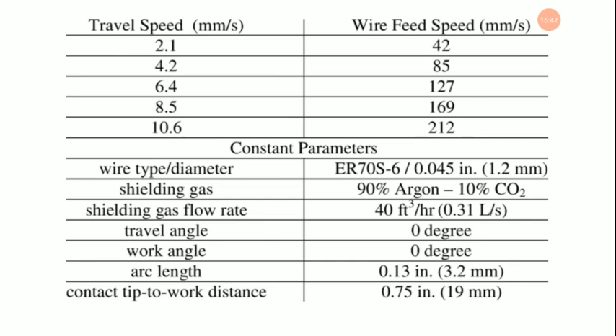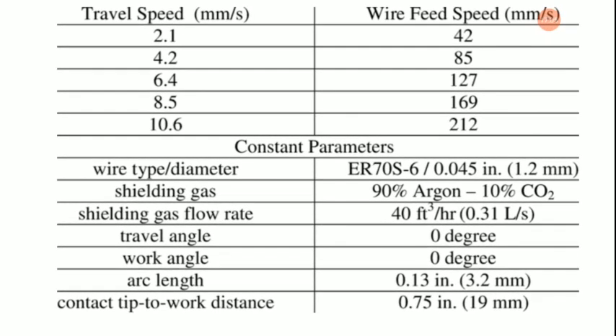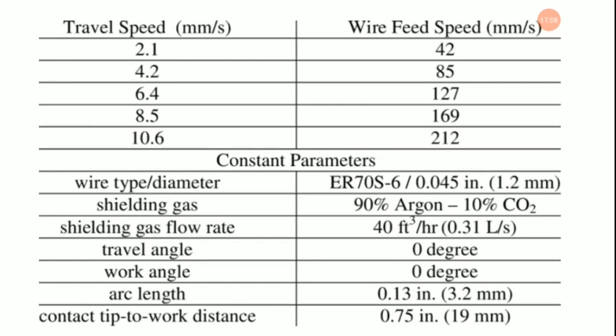Now, if we consider this comparative study, here you will find that when the travel speed is 2.1, the wire feed speed is 42. When the travel speed is 4.2, the wire feed speed is 85. When the travel speed is 8.5, the wire feed speed is 169. And when the travel speed is 10.6, the wire feed speed is 212, such that the travel speed is given in millimeter per second, while the wire feed speed is also given in millimeter per second.